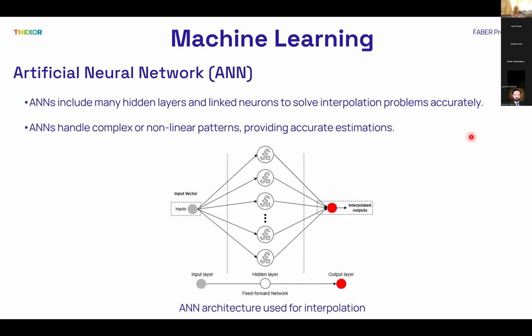So in our work, we used a feed-forward neural network, fully connected. The input layer was set to the stress amplitude and the thermal parameters. We used 3 hidden layers. In each layer, the first layer 128, the second 64, and the third 32 neurons. Obviously, we use ReLU activation with batch normalization to stabilize training, and we use a 20% dropout to avoid overfitting, and L2 regularization, and we use the Adam optimizer converging in less than 200 epochs, which is a normal setup for an artificial neural network.